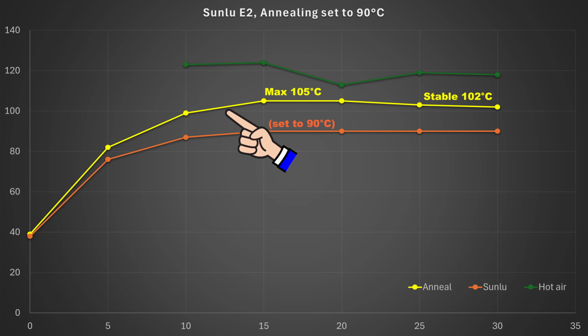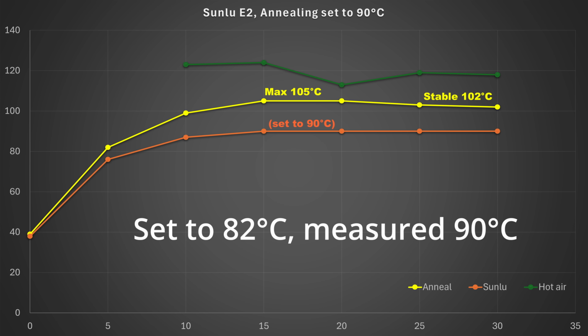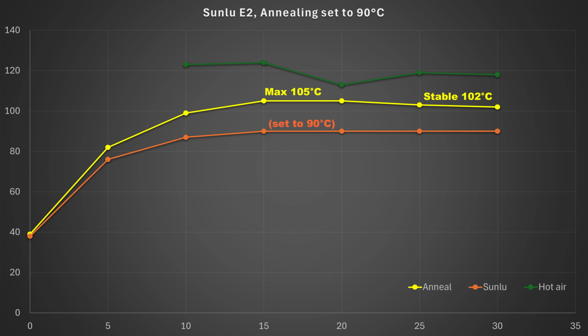On this graph, the yellow line is the most important, that's the annealing temperature, measured where our objects will be placed. And this means if we set 90 degrees Celsius, the stabilized temperature will be approximately 102. And only when I set it to 82 degrees Celsius, the stabilized annealing temperature was 90 degrees Celsius, which I usually use for my objects.